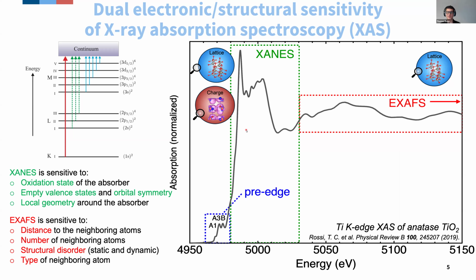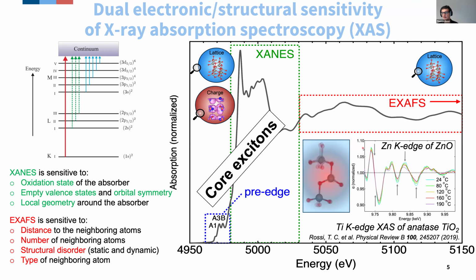And in our case, it's also going to be complicated because this is typically where we are going to find core excitons in the material. But although this is very complicated, there is something very nice that we can use in this spectra. It's the fact that we have one part of the spectrum, the EXAFS, that's uniquely sensitive to the lattice. So we can use the information it delivers to try to understand what are the consequences of lattice dynamics on the XANES, and then be able to extract what is the effect of the charges. That's the strategy.